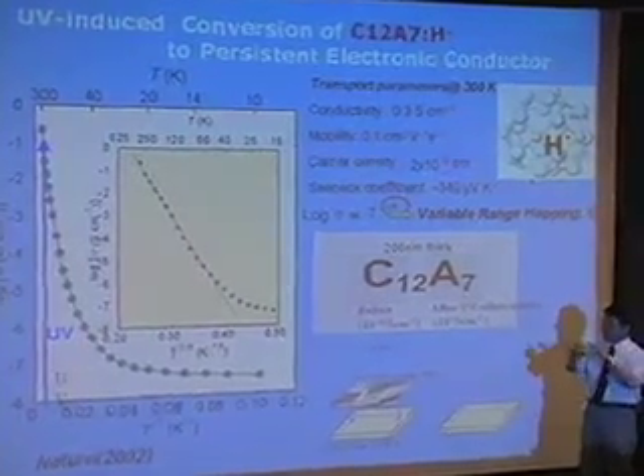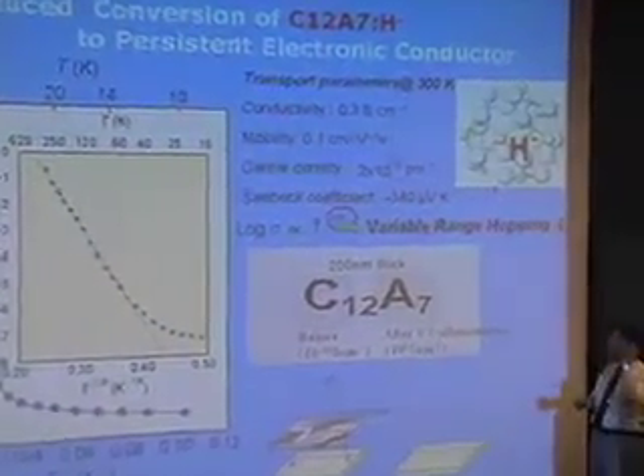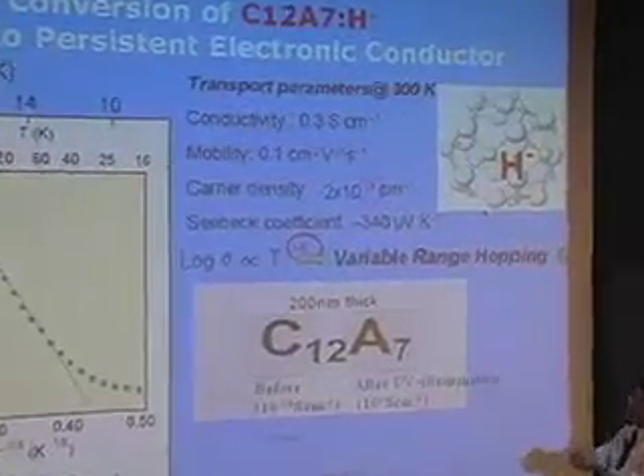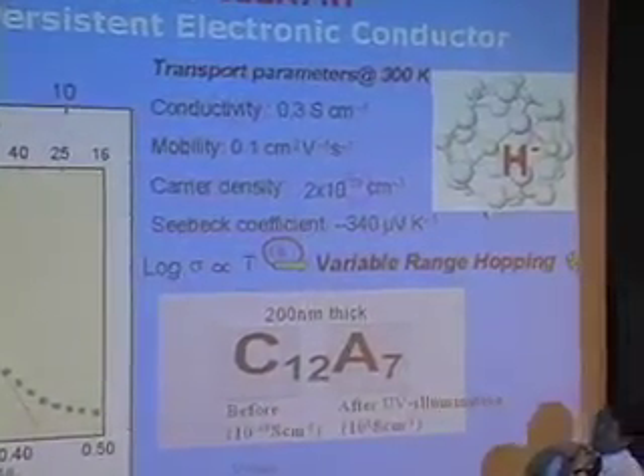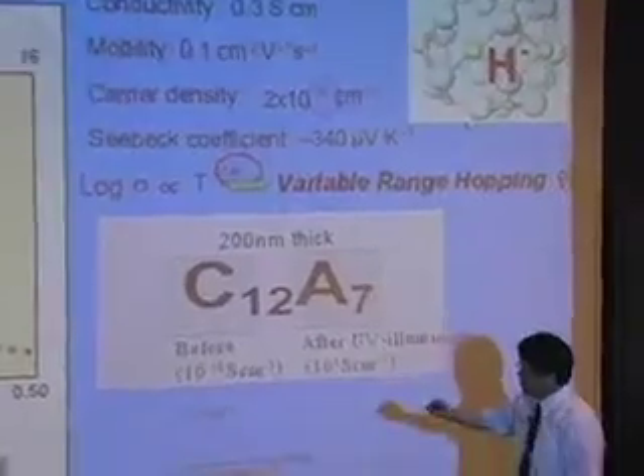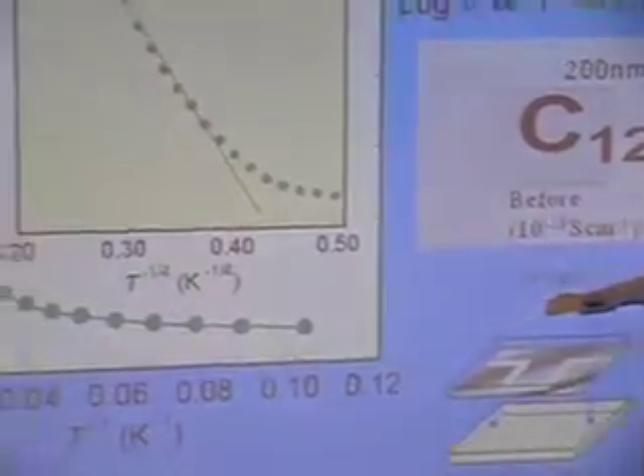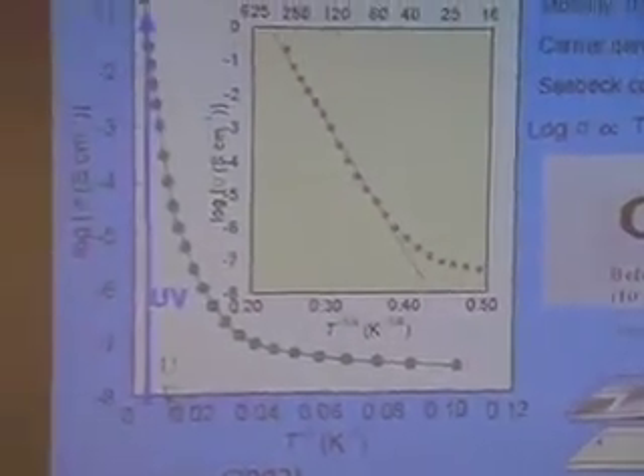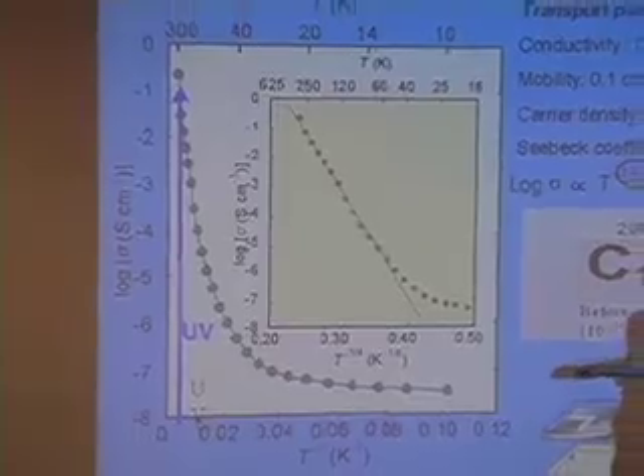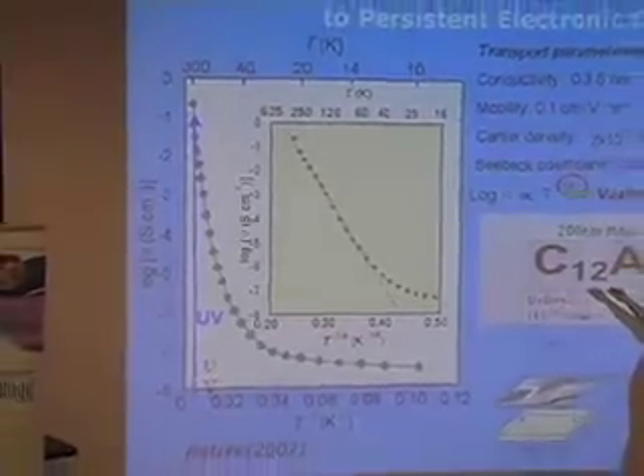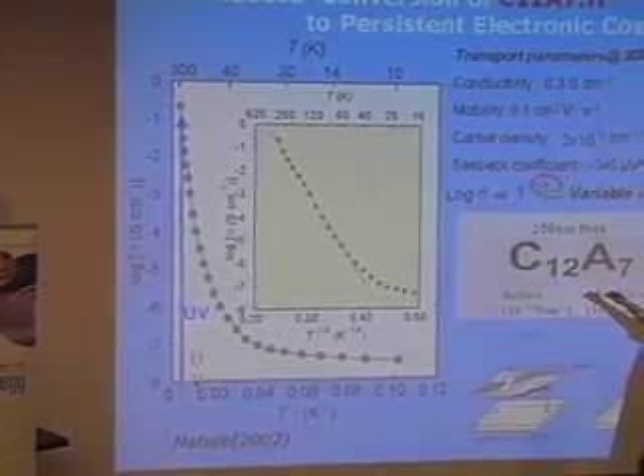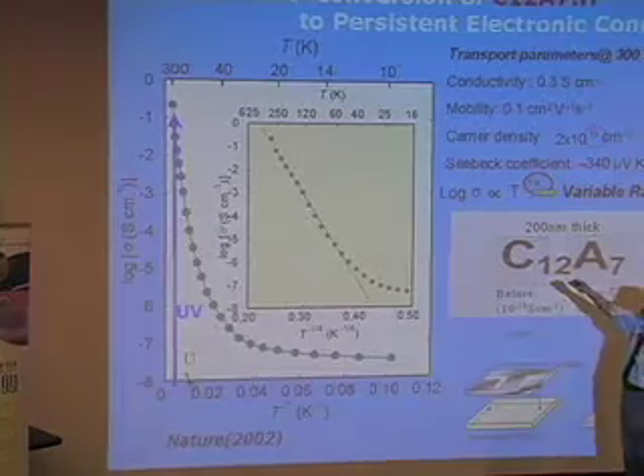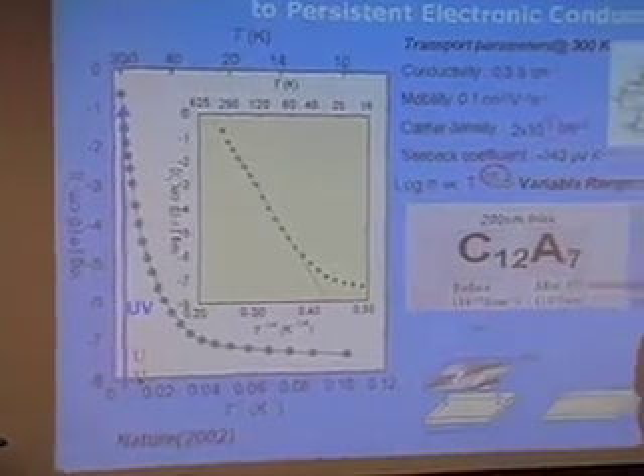It looks white, nothing changed. But when the hydrogen-treated C12A7 is exposed to ultraviolet radiation, what happens? Before irradiation, the sample is insulating, below 10 to the minus 10 at room temperature. When exposed to UV radiation, conductivity goes up over 10 orders of magnitude, reaching almost 1 or sometimes 10 at room temperature.